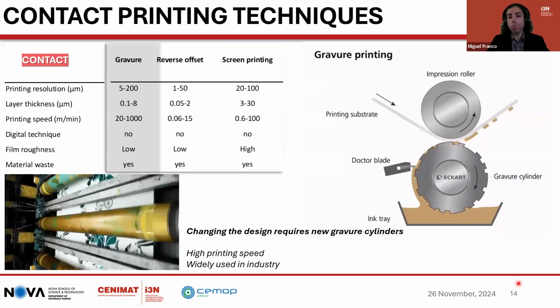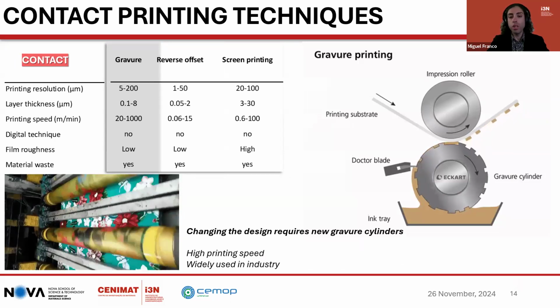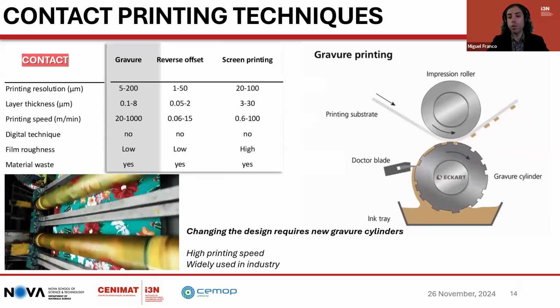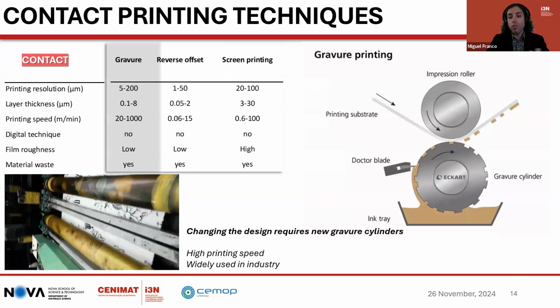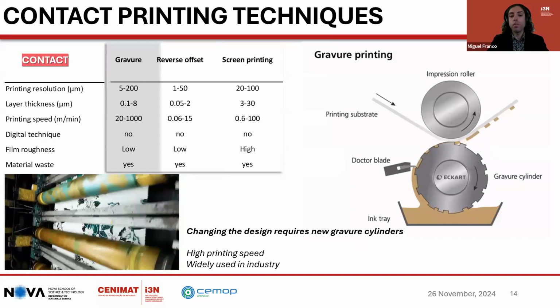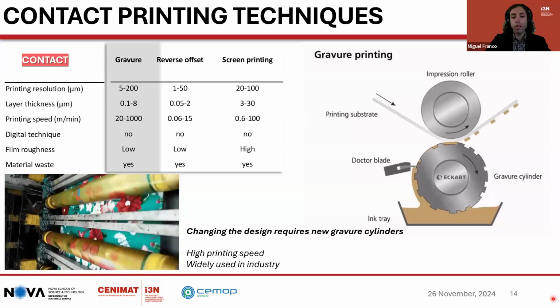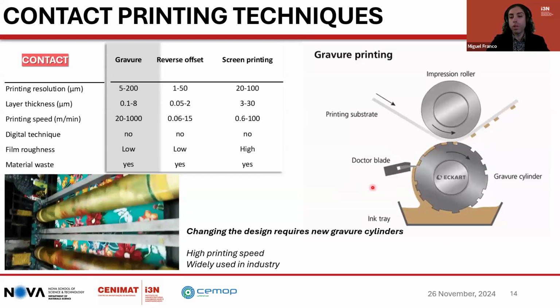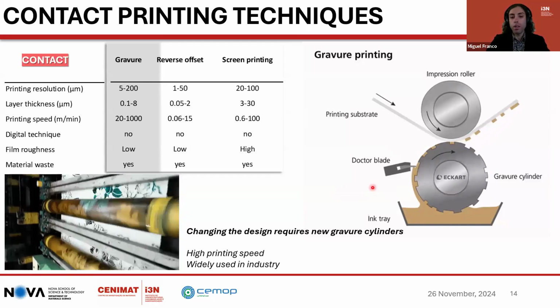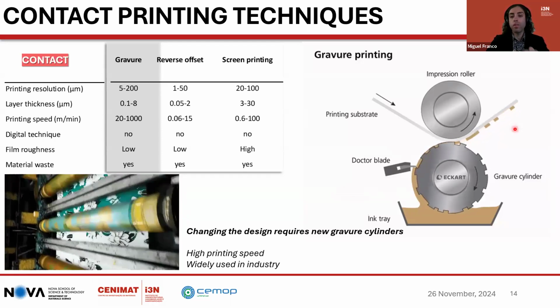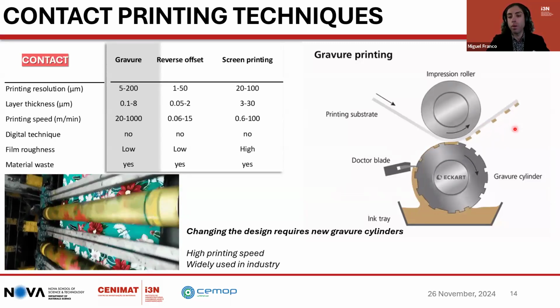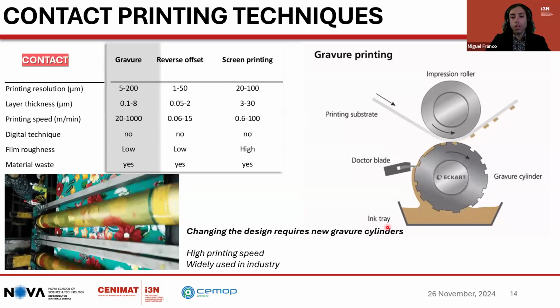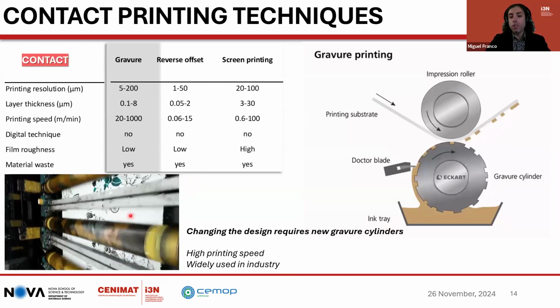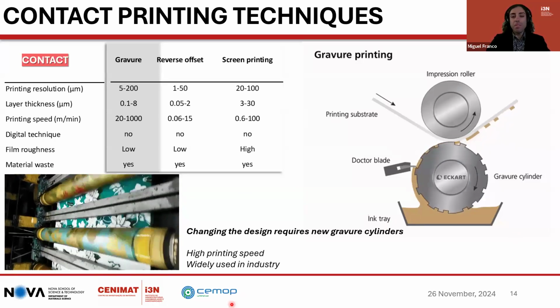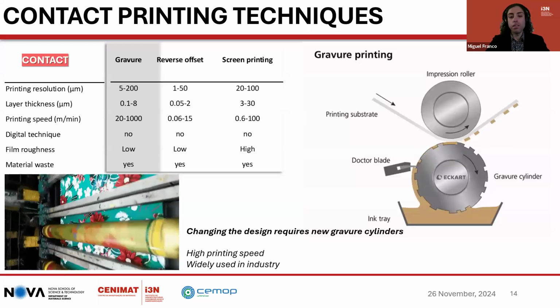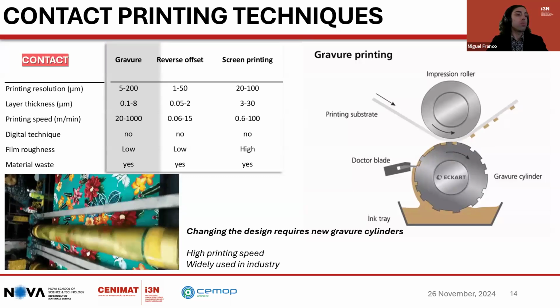Then I will introduce some contact printing techniques. We have gravure printing, where the design elements are engraved into a printing cylinder surface with a partially filled ink fountain. The engraved printing cylinder revolves. The entire surface of the cylinder collects ink from the fountain, where the excess is removed by doctor blades from the non-image areas, leaving the ink in the engraved cells. The ink is then transferred directly from the cells to the substrate in the printing nip under pressure. This technique is widely used in the graphic industry and permits high throughput. However, the main limitation of this printing technique at lab scale is that changing the design requires new cylinders, so it tends to be very costly.